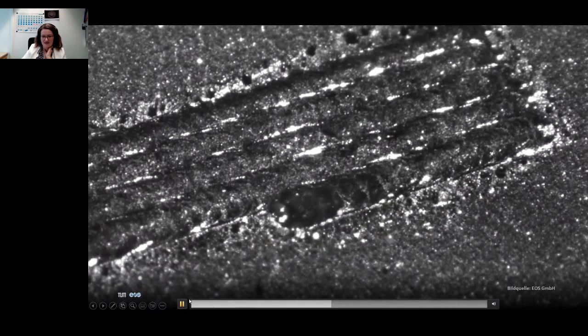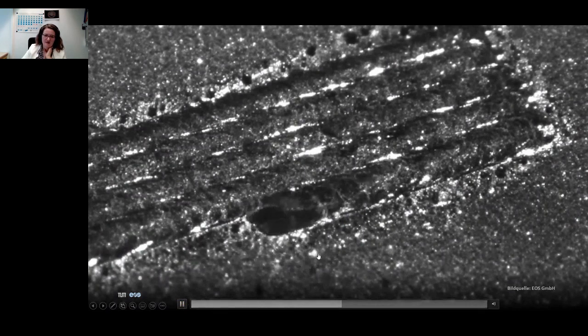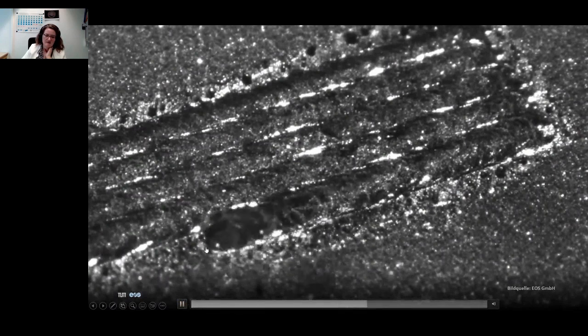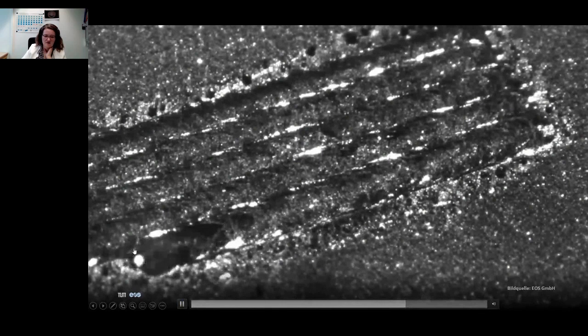But what you can see is you have here the powder bed. You cannot see actually a denudation zone, and you have a really, really smooth, less dynamic melt pool, and also the number of spatters you're creating here is way smaller. So these are the first results.